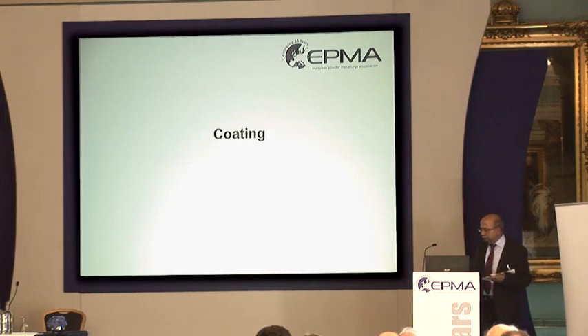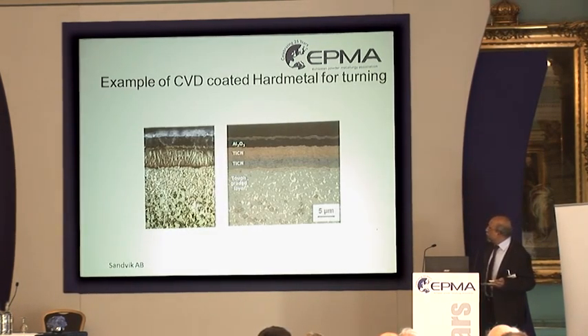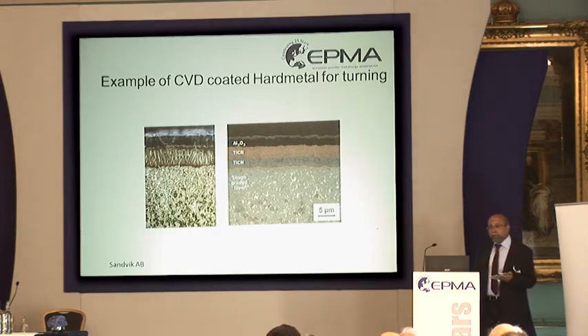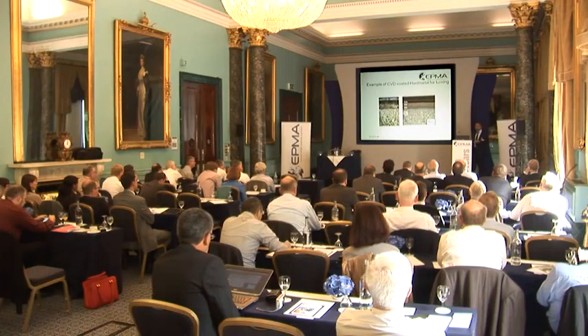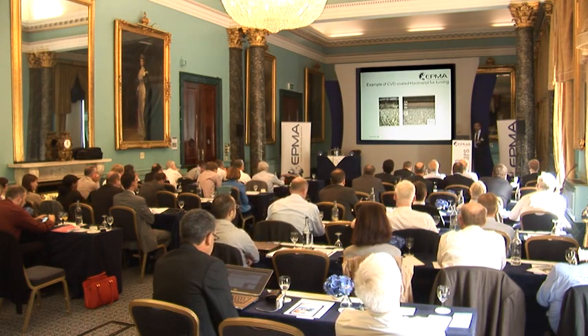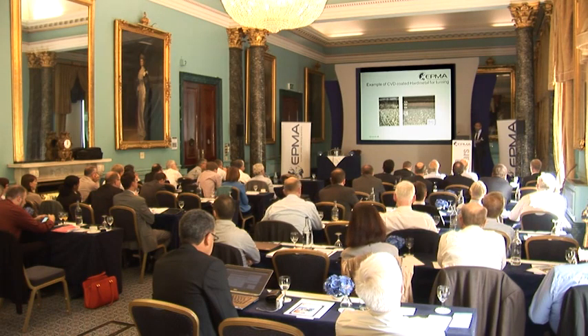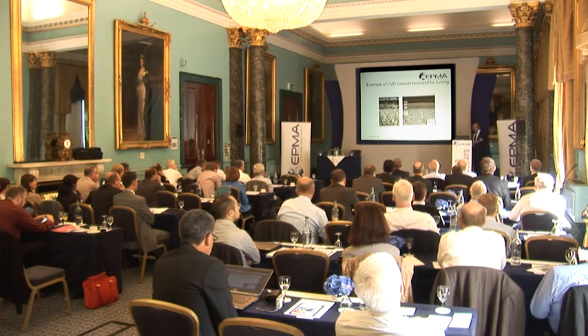A few words about coatings. Second life. You see here some examples of CVD coatings, multi-layer coatings, and the main improvement nowadays is in the aluminum oxide top layer coating, which gives the inserts higher wear resistance, chemical wear resistance, as well as high temperature wear resistance. So we can have coatings going up to 20 microns in thickness, and almost everybody says the lifetime is increased by 100%, but I don't know what the baseline is. But we can really believe the suppliers, because it's not just the coating, it's the geometry, coating, machine, holder, workpiece material, which is important, and 100% tool life increases are possible.